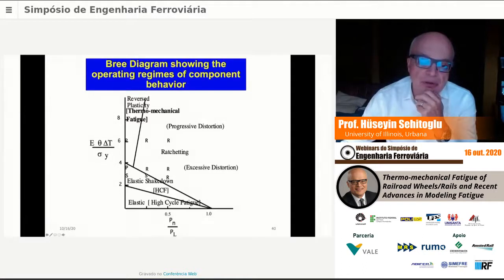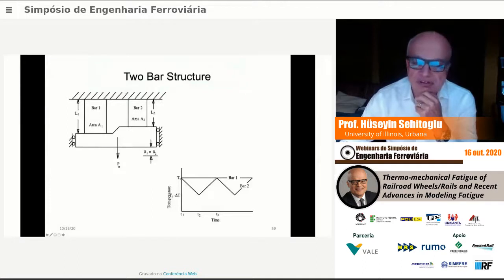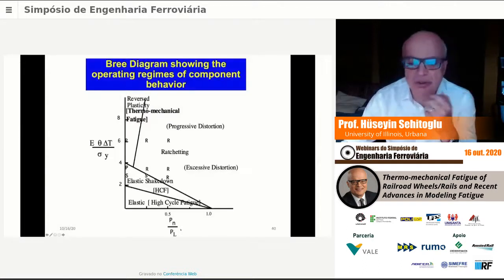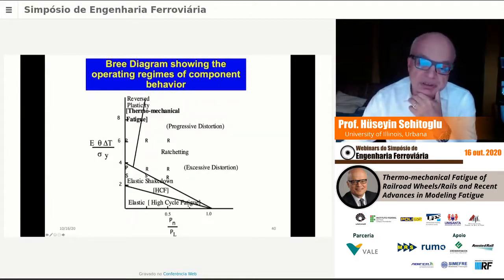So you plot the coefficient of thermal expansion, in this case denoted as theta, this is delta T, E, sigma Y. This is the thermal load. Sometimes it's called the secondary load in design. And this is the primary load, the applied net section load here. If your applied net section load is anywhere here, but your thermal load is small, you get elastic behavior. It's called high cycle fatigue.